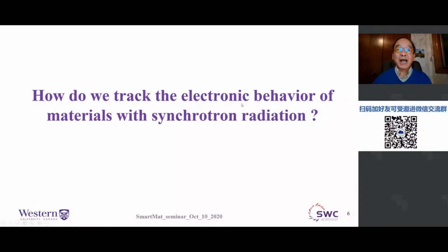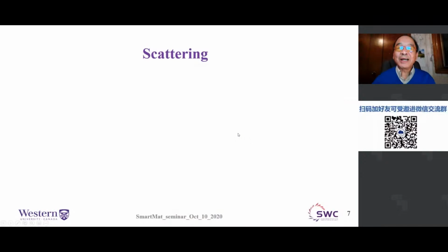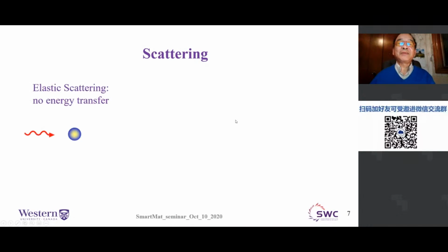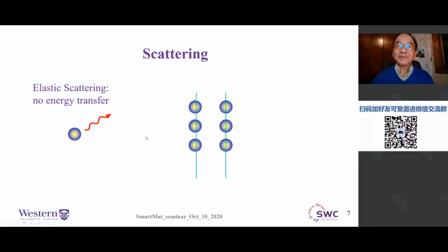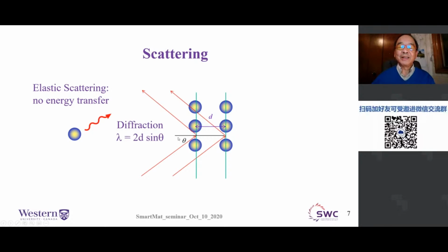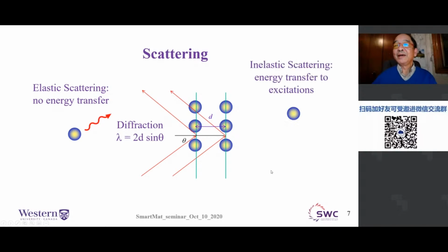Okay, so how do we track the behavior of material with synchrotron radiation? That's the key. The tracking can be done by scattering. Let's start from an atom. The X-ray comes in, it can be scattered. That means it changes direction. It does not lose energy. But if the scattering is done coherently by an array of atoms in a crystal, for example, if the wavelength matches the Bragg diffraction condition, then you can actually get diffraction. This is where X-ray crystallography comes in, and from where you can determine the crystal parameters using diffraction.